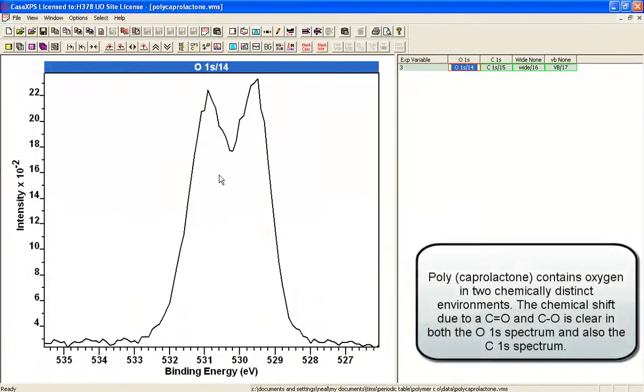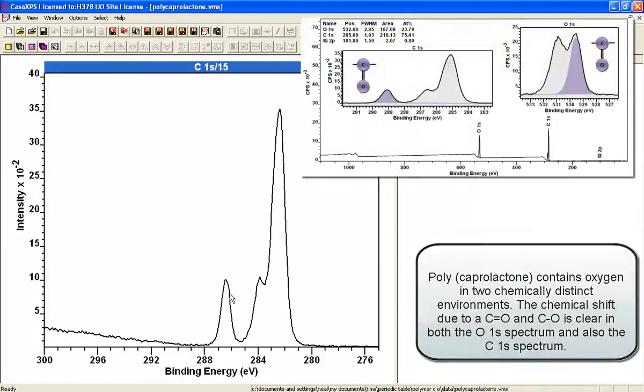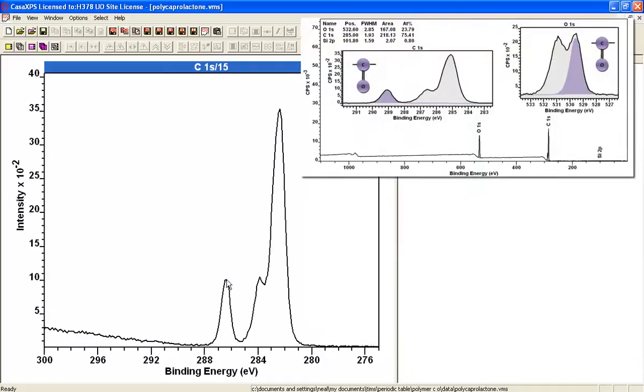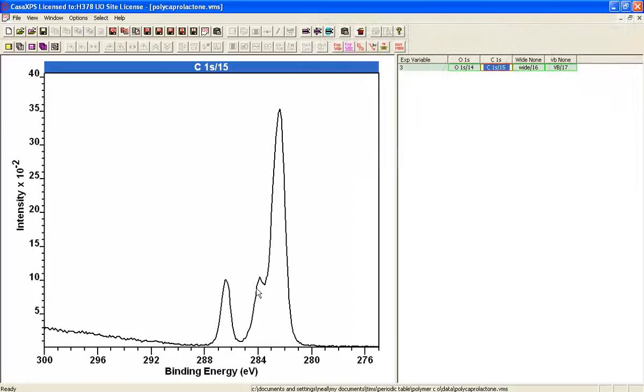There are two peaks within this oxygen envelope and these two peaks correspond to two peaks within this carbon where you have a C double bond O and a C single bond O peak here.